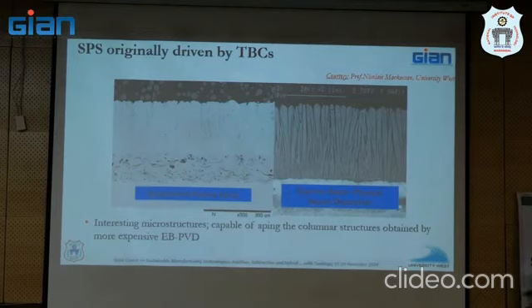Why are some groups crazy about using suspensions? They're crazy because it was soon found that you could get columnar coatings like this if you used submicron particles in a suspension. This is the main driver. It's not exactly like an EBPVD columnar coating, but it's close. It gives the same effect. What is that effect? It gives you the strain tolerance because it has this finger-like structure. So when you have heating and cooling, it can expand and contract and therefore accommodate stresses, correct? That is very crucial in a thermal barrier coating, which sees thermal cycling. You want this to happen, right?